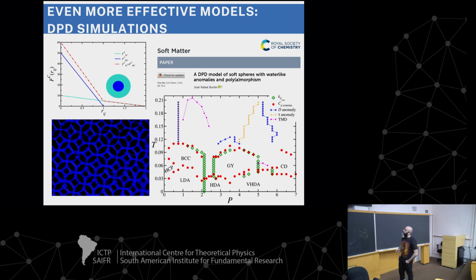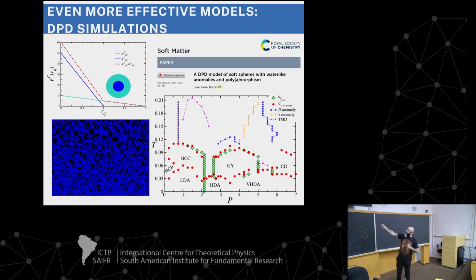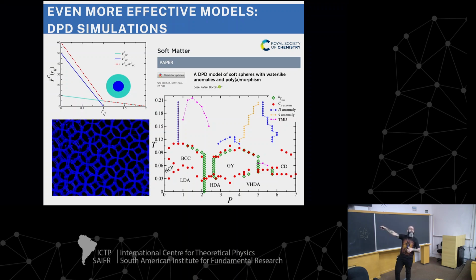And well, this is the phase diagram, and it's nice because this phase here is a gyroid phase. Actually, it took me like 3 months to finish this paper because I could not understand what this phase was. The system has the HCP solid phase, a BCC phase, a cubic diamond phase. It shows 3 amorphous phases: low-density amorphous, high-density amorphous, and very-high-density amorphous. And this phase here, just returned, is this one. It was published in 2022 in Nature, where they found this kind of structure for the first time. For this reason, it was really hard for me to say what this was.